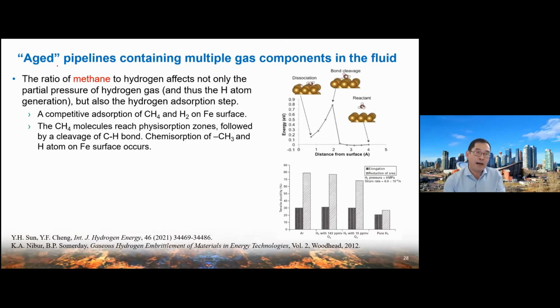Number four, for the aged pipeline used for hydrogen transport, how will impurity gases influence hydrogen embrittlement, particularly methane, CH4. Our research proves that if CH4 is available, it will compete with the hydrogen in terms of adsorption on the steel surface, but the bonding energy of methane compared with the hydrogen adsorption energy will be different. The energy difference will depend on the temperature and the percentages of hydrogen and methane, and finally will influence how much hydrogen competes with the methane to touch the steel surface and go into the steel. So we need a model to quantify the competition effect of methane on hydrogen permeation. That's the first impurity gas.